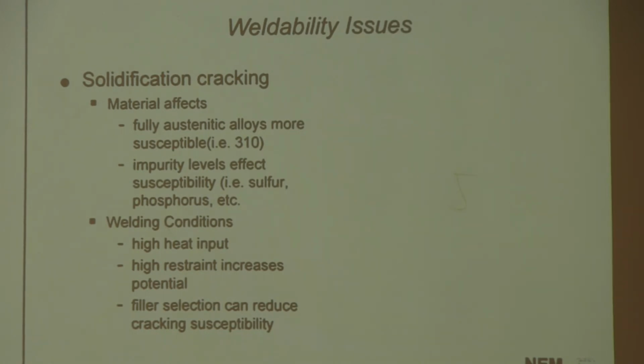And also impurity levels like sulfur and phosphorus, because when a material solidifies, those impurity elements, as the material grows together, get transferred to the boundaries that are created, and they end up creating a low melting phase or a eutectic phase, which is much more susceptible to being pulled apart as the shrinkage stresses are created during solidification.